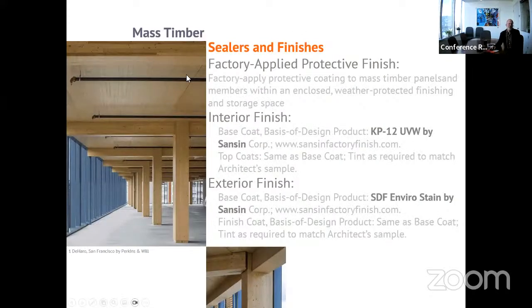Sealers and finishes are important both for the protection of the wood during the construction and its appearance following construction. As Maria Paola noted, in the factory, they can apply either a liquid coating or a self-adhered membrane. We often request that that be installed in the factory before the panels arrive on site. This is so that once they're on the site, we don't have as much moisture moving into and through the panels and staining the materials down below, but also simply in our environment here with so much moisture, to avoid the excessive moisture and potential for mold or other problems inside the building later.